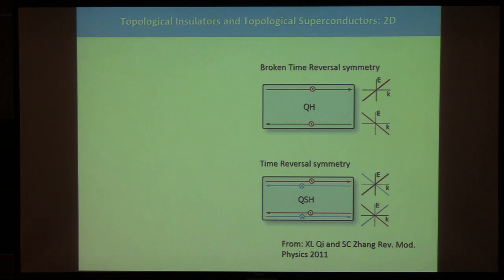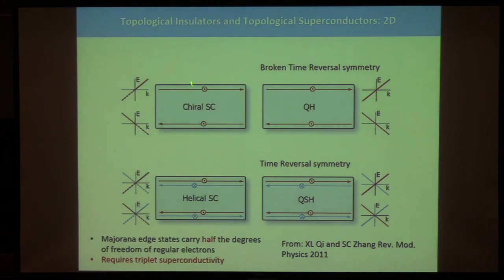So to give a few examples of conventional topological insulators, here is one. That's a topological insulator, a quantum Hall state, where we know that the bulk is gapped and it has edge states on the surface, and these are in fact chiral because this system breaks time reversal symmetry. A quantum spin Hall state is another topological insulator that now satisfies time reversal symmetry, so it has two chiral states along the edge while the bulk is gapped. And in analogy with those, we have topological superconductors. And here is an example of a chiral topological superconductor. So this is now a superconductor where the bulk is gapped due to superconducting correlations, and yet the edge hosts chiral excitations. And this is a helical superconductor, one that has counterpropagating edge states.